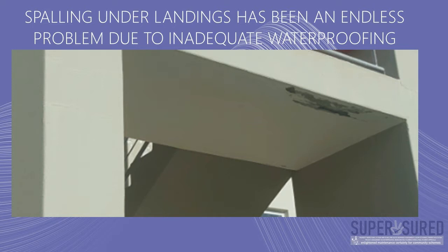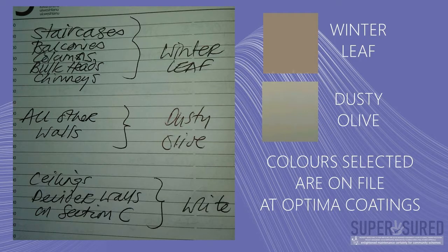Now, the main problem in investigation is what I suspected, and that is that the walkways and underneath the balconies is where the water is coming through. There was one area where the white paint, in fact, there's probably two areas, but on one block, the white paint that was used was not Elastomeric, it was a Dulux ordinary white paint, and there you can see how it's actually peeling. Whereas the Elastomeric product which we used, which was in the three colors, you'll see on the screen now the colors that were selected: dusty olive and winter leaf. Winter leaf being the darker color, dusty olive being the primary color. And that was mixed by Optima.